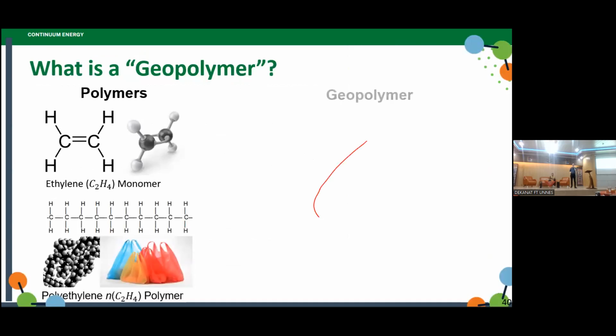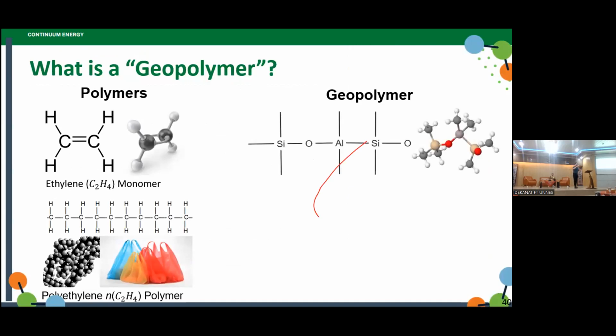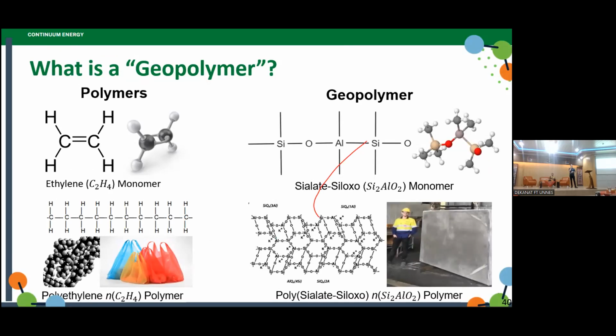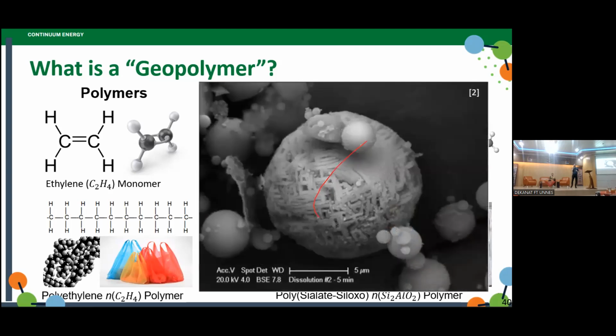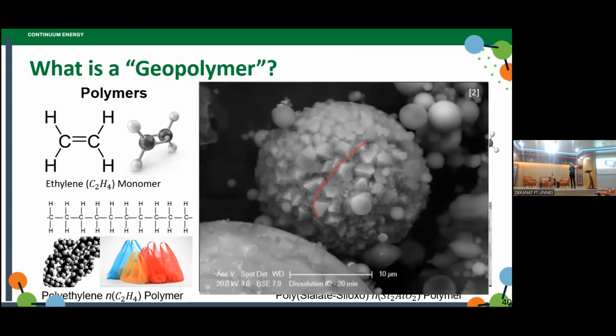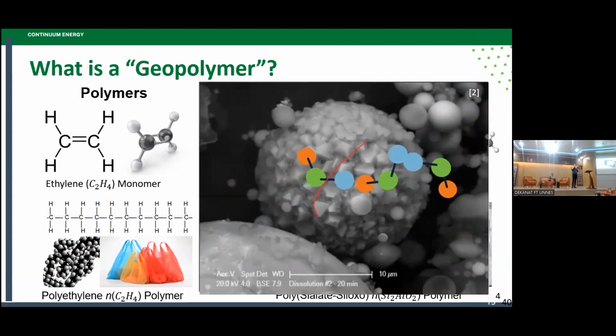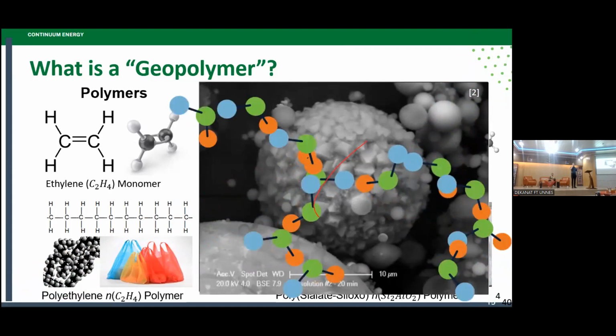But when it comes to making geopolymer, just the technical side of things: a polymer is essentially where you have normal monomers such as ethylene, a carbon-hydrogen combination, to make polyethylene, which is plastic bags. A geopolymer is simply a combination of silicon, aluminium, and oxygen. Next slide. And this is what it looks like under the microscope. So this is a coal fly ash sphere. And as the geopolymer is made, next slide, you can see that they form, and then the activating chemicals form, and then all combine to make a long polymer chain, which is what gives the concrete its strength.